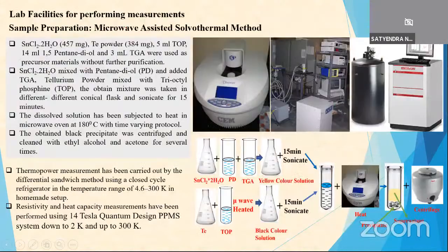We have used lab facilities during the synthesis of the sample and several measurements, to consider the effect of the phonon scattering mechanism. So we have used the precursors pentanediol and SnCl2, heated with a microwave oven, and tellurium has also been heated in TOP, and we are changing the protocol of the time for the 4 samples. We are changing the vacancies of the tellurium growth. So there is an enhancement in the tellurium occupancies as well as the temperature protocol in the system. We have carried out the thermopower measurements with a differential sandwich method homemade system in our lab, and this is the commercial PPMS system.